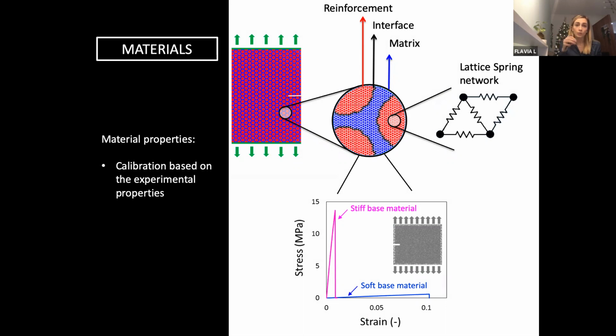What happens is that during the curing, these materials have a really low viscosity, which means that you can have a mixture of them. So a third material is formed at the interface. And this is also proved by the fact that in the end, we never get a failure at the interface. The materials are perfectly bonded due to the formation of a chemical bond, and the formation of another material.